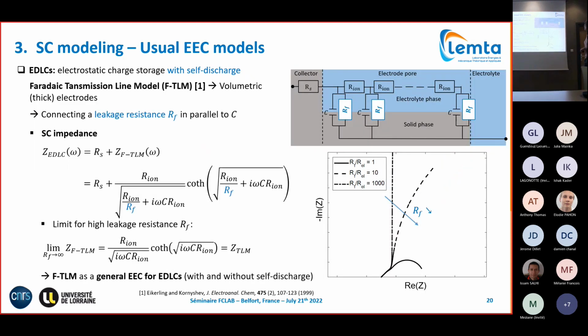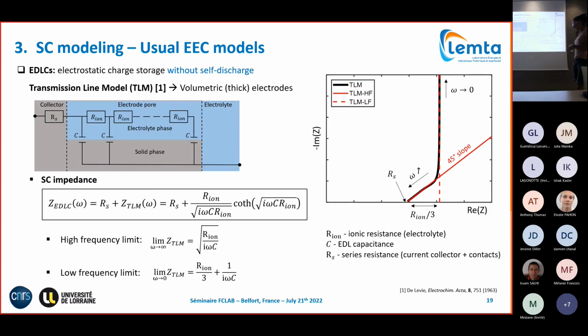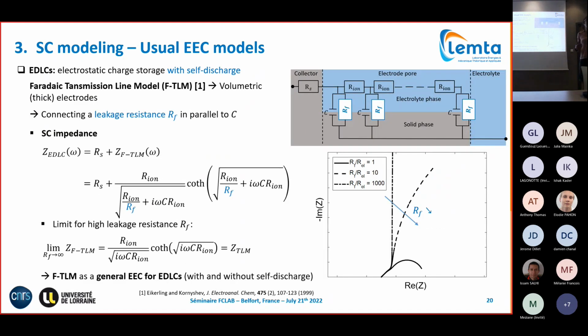Okay, so that's the ideal supercapacitor without any self-discharge. Reality is different. You always have some self-discharge phenomena in the device, which can be due to the redistribution of the charges inside the pore space. How to model it is simply by connecting a leakage resistance in parallel to the capacitances in your circuit. This means you have an additional parameter in your impedance expression. The lower the leakage resistance, meaning more self-discharge, the more your low-frequency line deviates from the vertical line.